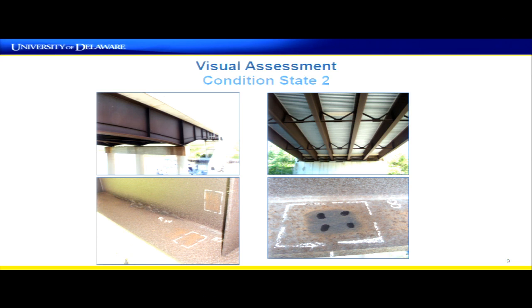However, this bridge on the top left, you can probably see, depending on the lighting, this is crossing a navigable waterway. Not only that, it's crossing a navigable waterway less than 1/10 of a mile from the Gulf Coast in one of the most humid locations of any of the bridges we looked at, with the highest atmospheric chloride concentrations of any of the bridges we looked at. And so there was a lot of debate during the research whether this level of corrosion, the bridge is also close to 40 years old, is really a problem, or is weathering steel really doing a good job here? For example, would paint be performing better, or any of the other systems that are commonly used? So yes, this is pitting, but not necessarily an indication that weathering steel was the wrong choice here.